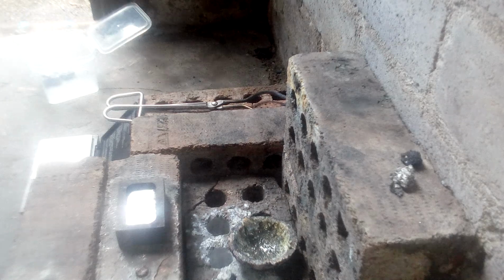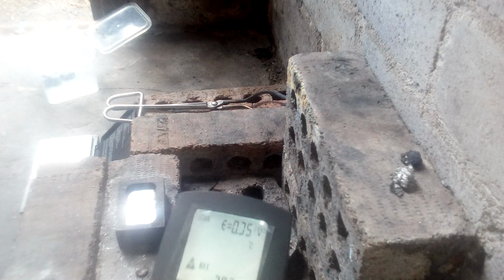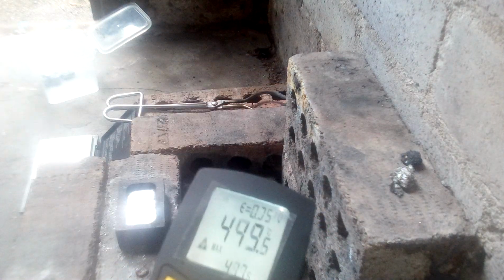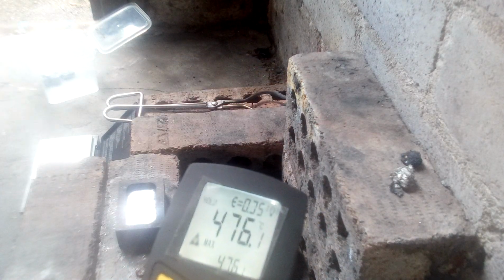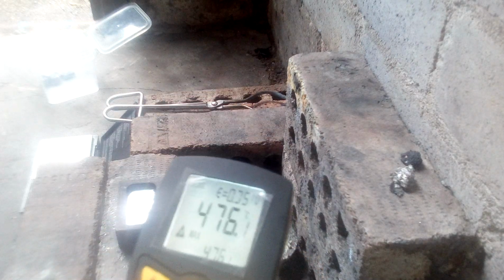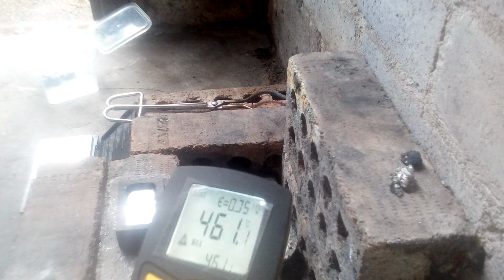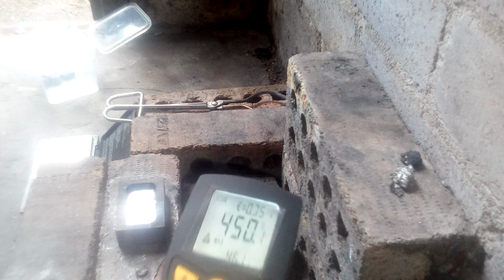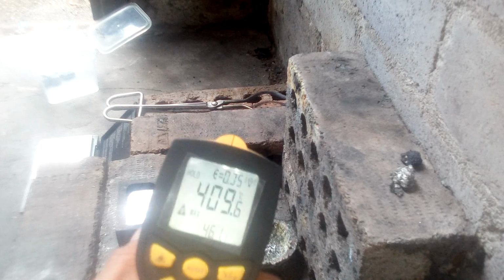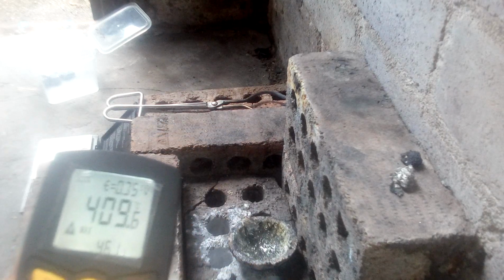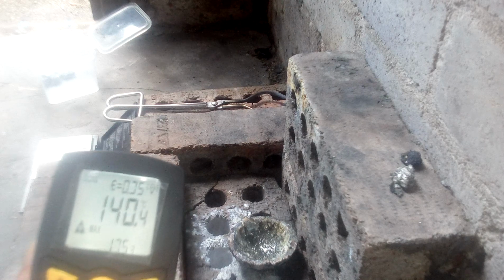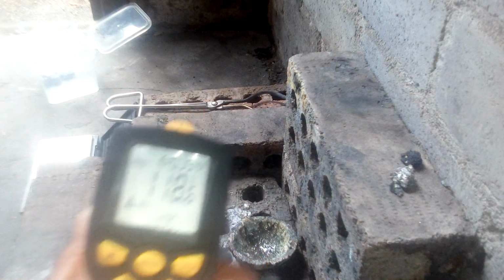Take my goggles off now. Let's check the temperature on the crucible. Ooh, that's high. So nearly 500 degrees on the crucible. Enough to melt the borax. It was obviously much hotter just now when I had the blowtorch going. And the mould is quite low temperature.